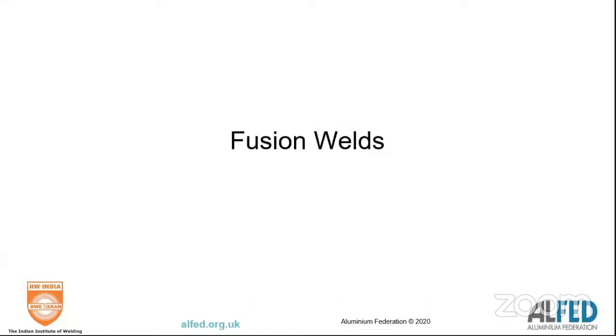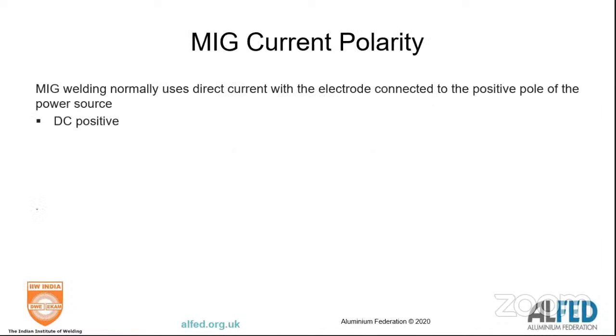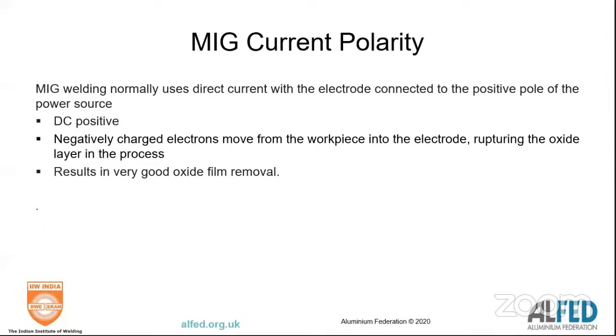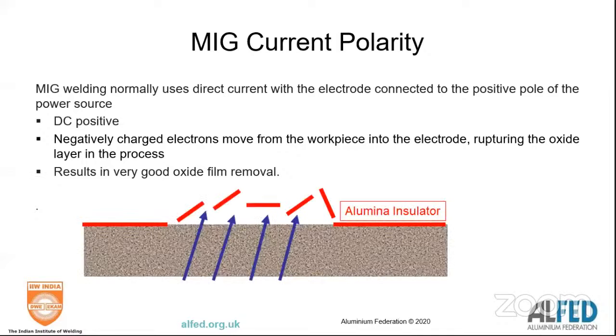So let's talk about a big process of welding aluminium, so fusion welds. If we talk MIG, the beauty of aluminium is you would be DC positive welding. So you connect the positive pole to the power supply. That means that the negative electrons are coming out of the workpiece towards the electrode. In essence, because they're coming up behind the oxide layer, they are actually breaking up the oxide and lifting it up. In essence, there's a chemical reaction coming in. Electricity is the flow of electrons. A couple of electrons are bonding with oxygen to produce an oxygen molecule, lifting the oxygen off. So MIG, when you're using DC positive, because you want to melt your filler rod, self-cleans. If you're doing automated MIG in the UK, a lot of the people are still removing the oxide to speed up the process.